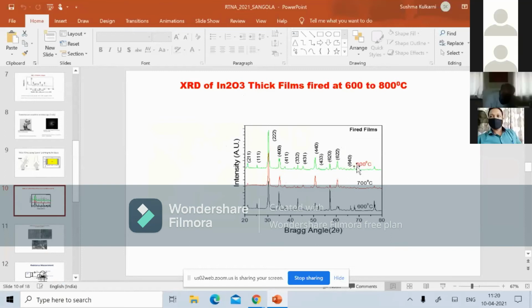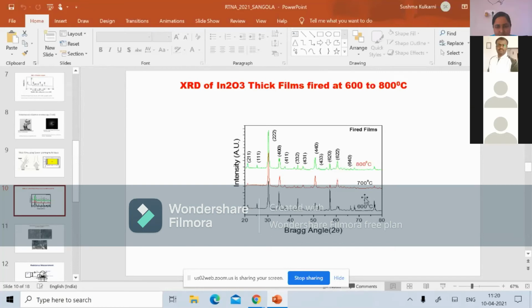And here we measured the crystallite size using the Debye-Scherrer formula, which was found to be 13 nanometer, 14 nanometer, and 16 nanometer. That is, 13 nanometer for the film fired at 600, 14 for 700, and 16 for 800. And after that, we have optimized the film.